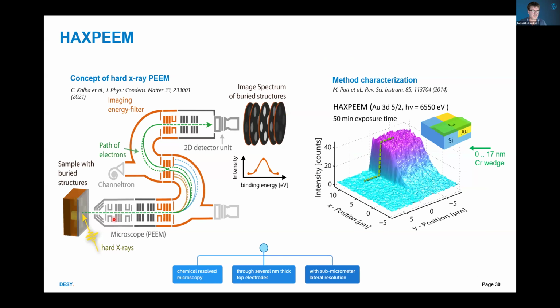Now we come to microscopy experiments, and the proof of principle was done about 10 years ago. This is the standard photoelectron emission microscope, but combined with the hemispherical analyzer, so you can get the image of your sample with energy resolution. Very simple principle. For example, here we detect the intensity underneath a chromium wedge from a gold sample, and we see that the imaging works pretty well, and the spectroscopy information corresponds to gold underneath chromium.